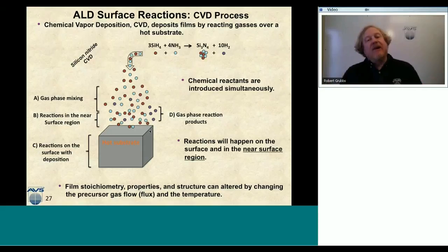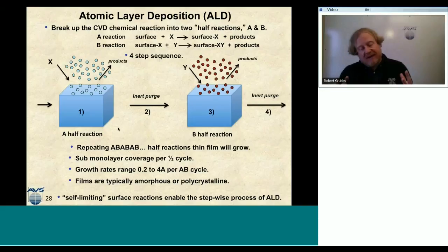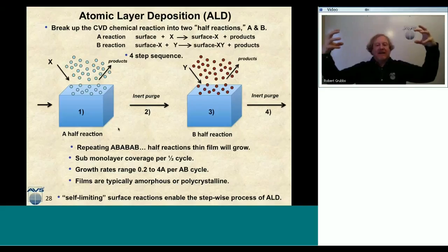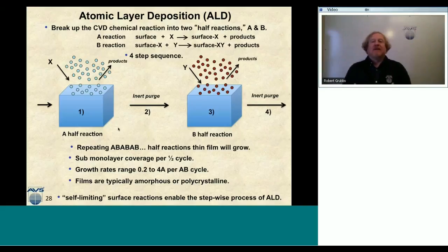So with CVD, we know that we bring these reactants in simultaneously. We know that there's a near surface region of chemical reactivity right above the substrate surface. So now let's contrast that with the ALD process. So here's the cartoon of the ALD process. The primary difference between chemical vapor deposition and atomic layer deposition is that in CVD, we bring the reactants in simultaneously, but in ALD, we bring the reactants in sequentially.